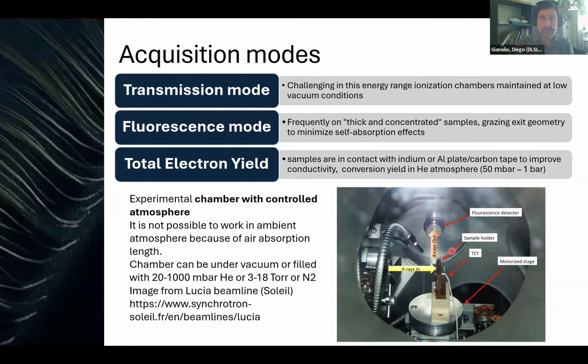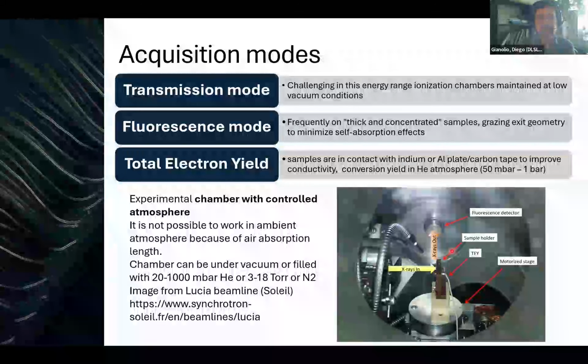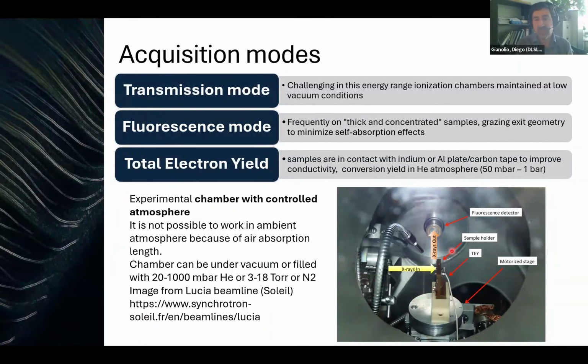Another acquisition mode that is less commonly used in hard X-rays, but may be more common in soft X-rays, is to measure total electron yield. This is possible if the samples are slightly conductive, and in general, the samples are then mounted in contact with an indium or aluminum plate or a carbon tape to improve the conductivity and be able to measure the current coming out of the sample as a result of the X-ray excitation. And there are also methods to increase the signal by using a partial helium atmosphere in the chamber that gives a better conversion yield.